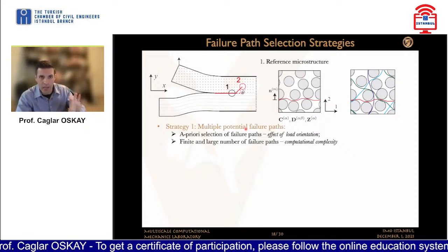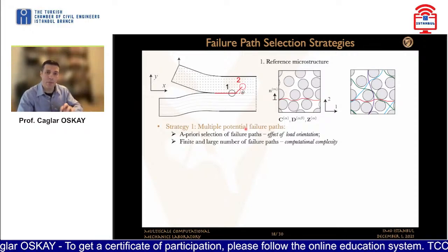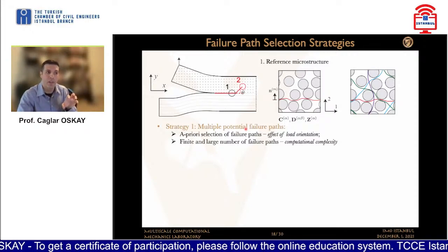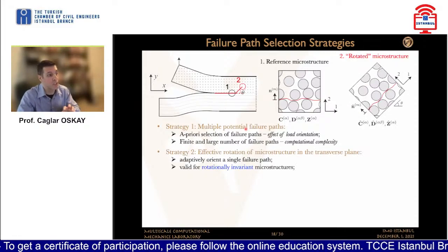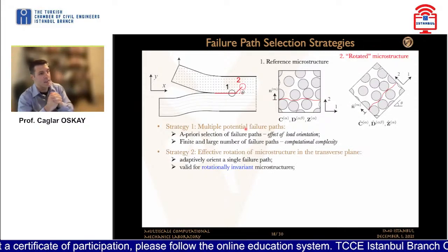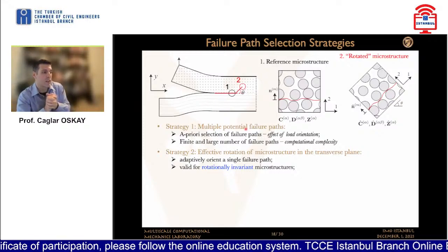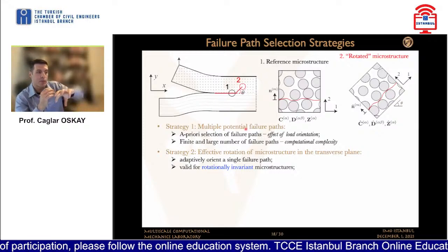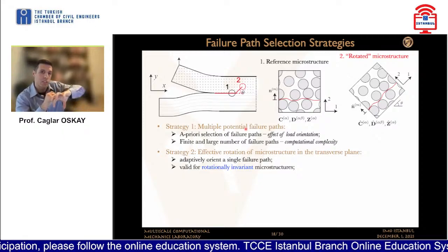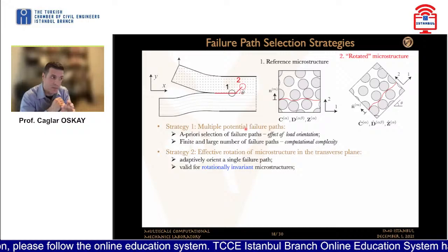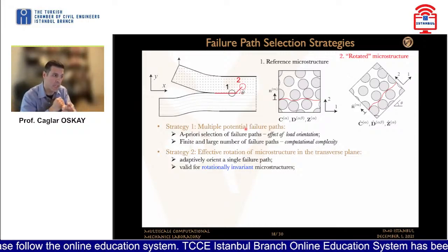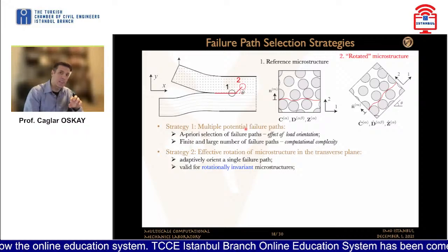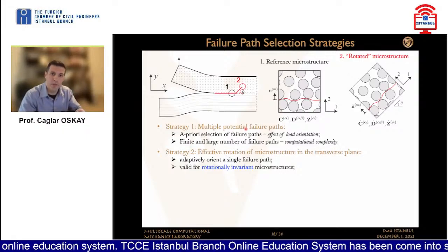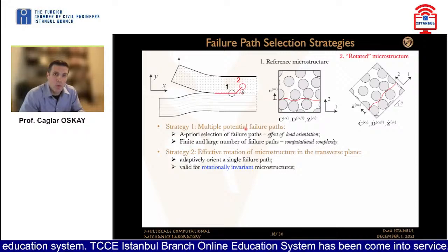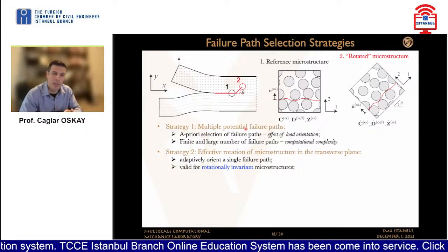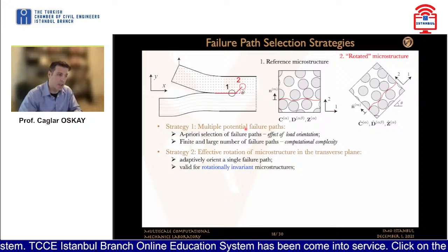Another simple idea that we have come up with is leveraging the rotational invariance of the microstructure when it comes to matrix cracks. If you consider a rotationally invariant microstructure, instead of rotating the crack, what we can do is rotate the microstructure along the invariant planes. And if that is the case, then instead of incorporating multiple failure paths, we can incorporate only a single failure path in that invariant plane and simply deal with the orientations.